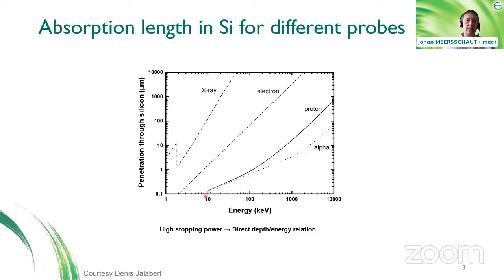You also see that in order to have some penetration into the material, you need a beam of at least around 10 kilo electron volt. And we speak about 10 mega electron volt to have a penetration depth of several microns. So it's important to consider that the range of ion beam energies that we will deal with is of the order of 10 kilo electron volt to 10 mega electron volt.